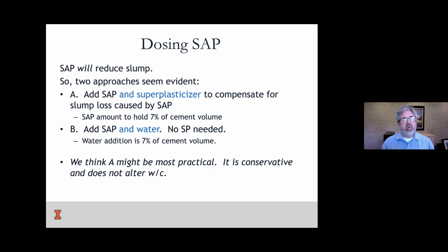Dosing SAP. We know that SAP will reduce the slump. And so we somewhat have two choices to make here. A, we could add the SAP, suffer the slump loss, but then add in a superplasticizer to compensate. And that would allow us to have in our mind that we're not going to change water. We're going to use the original mix design and count on superplasticizer to sort of offset that workability factor.